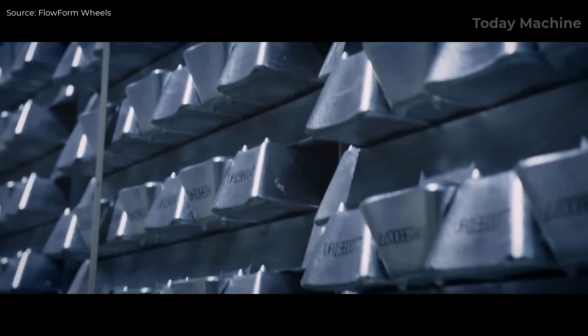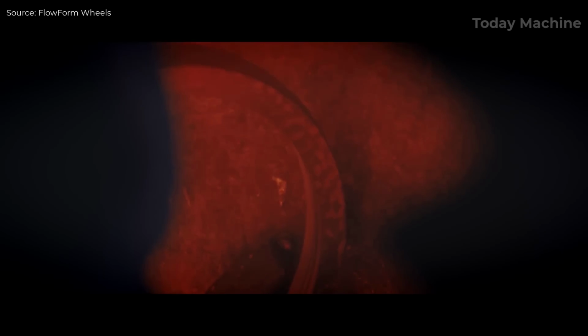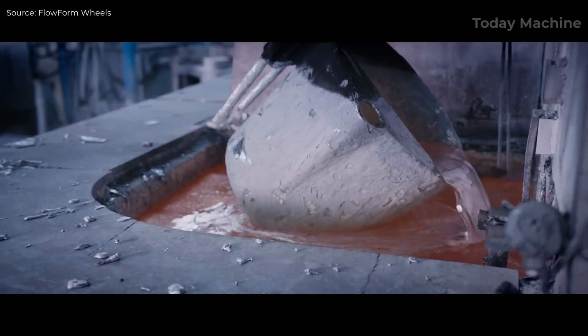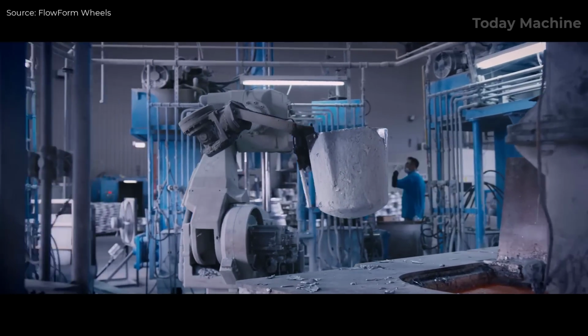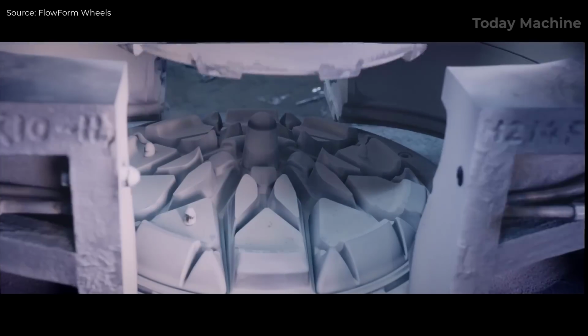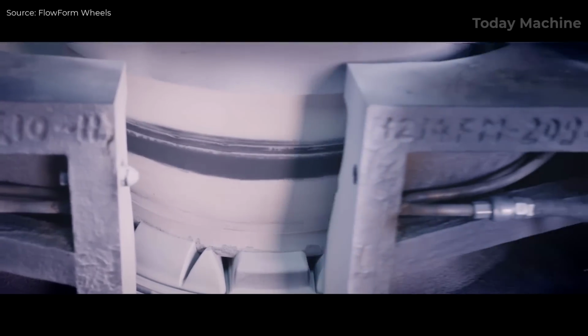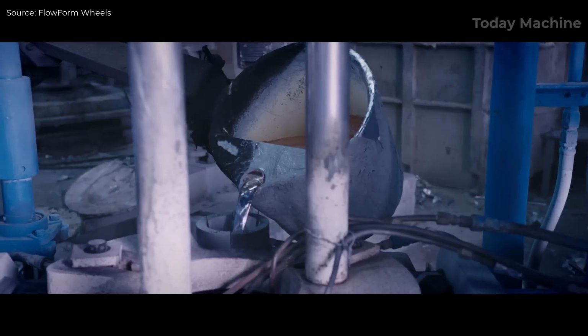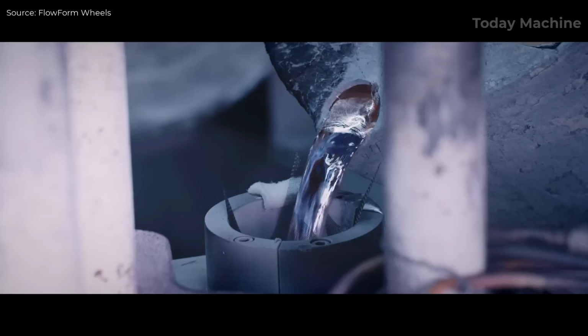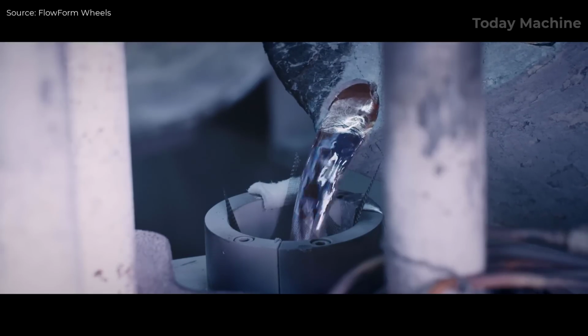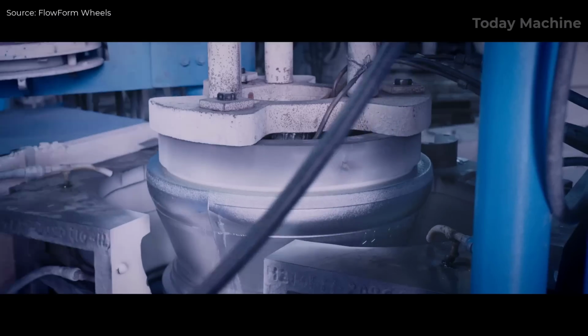The production process starts with a bar of this aluminum alloy, which is melted in a furnace at approximately 1,400 degrees Fahrenheit, 760 degrees Celsius. The molten aluminum is filtered, degassed, and inspected before being poured into a steel mold, which forms the wheel's face. Depending on the mold size, between 50 to 100 pounds of molten aluminum, now at over 1,300 degrees Fahrenheit, 704 degrees Celsius, are poured into the mold.